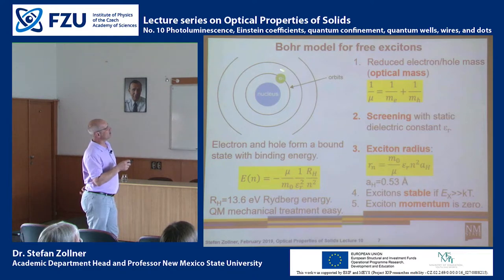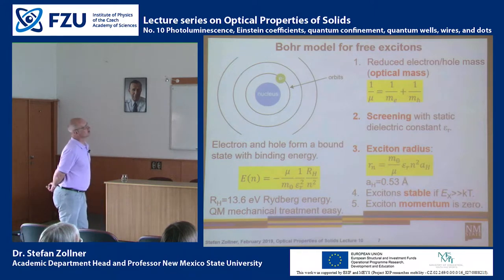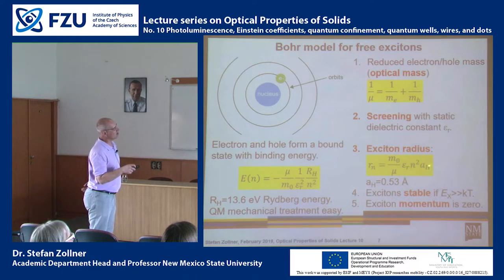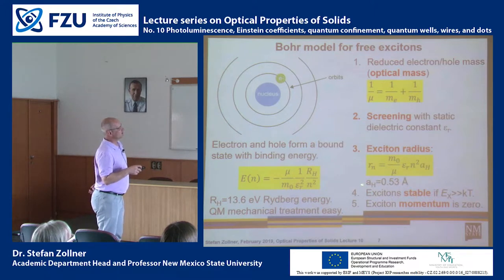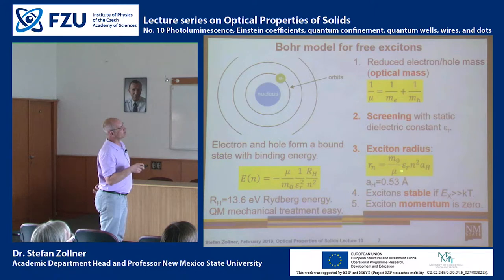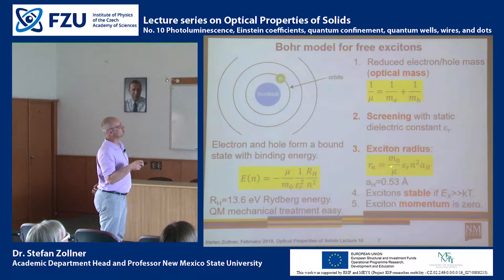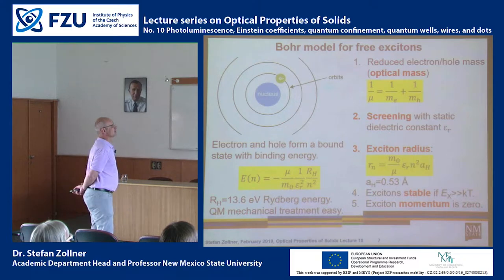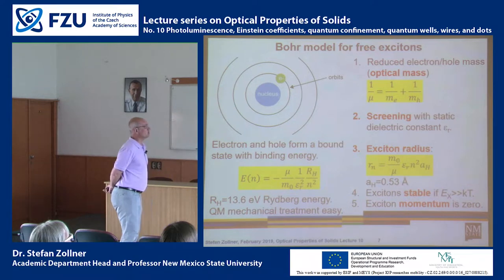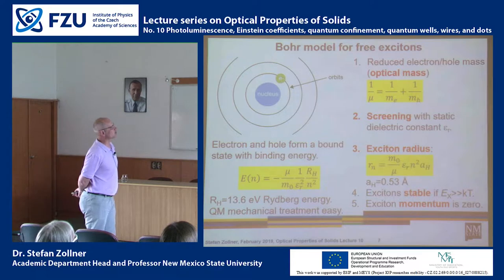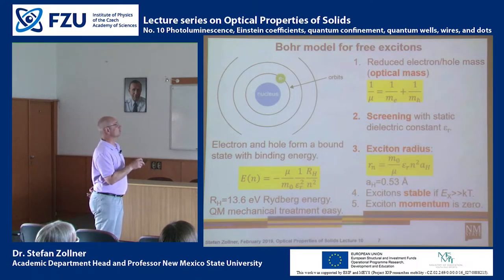The radius of the first shell of the hydrogen atom is the Bohr radius, 0.53 Å, and the n-th shell is n² times the first Bohr radius. For an exciton, the Bohr radius must be multiplied by the screening constant and by the inverse of the reduced mass — each factor is about 10 — so the excitonic radius is about 100 times larger than the Bohr radius, on the order of 50 to 200 Å.